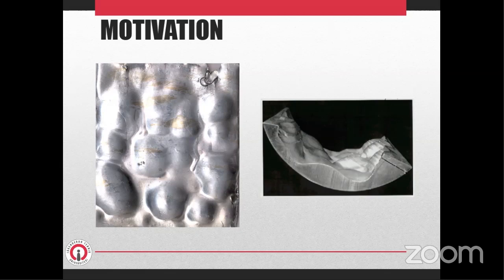Undesirable cracks have significant effects on the strength and microscopic structure of the ingot, and accordingly the quality of the final cast products is reduced. This leads to a waste of extra energy, workforce, raw material, and cost. Our aims in these studies are investigating the instability mechanism in the solidification process during casting of pure metals, improving our knowledge about this thermoelastic instability mechanism, and determining the conditions which eliminate or minimize the profile defects.